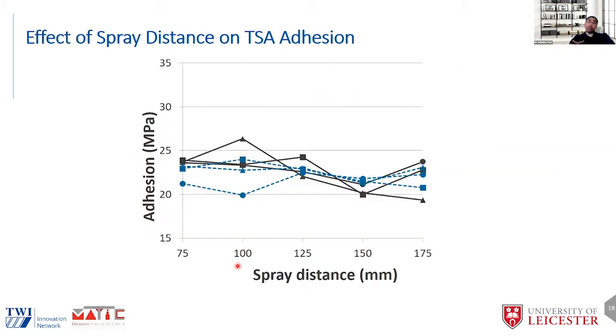When we looked at the effect of spray distance, again, here you can see adhesion on the y-axis in megapascal, spray distance in millimeters. So this is a standoff distance of the gun from your substrate in millimeters. And here again, we can see they vary between 20 to 25 megapascal in most cases, which is also very typical for thermal spray, arc spray aluminium.